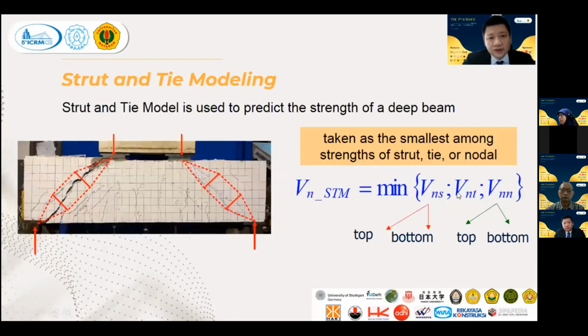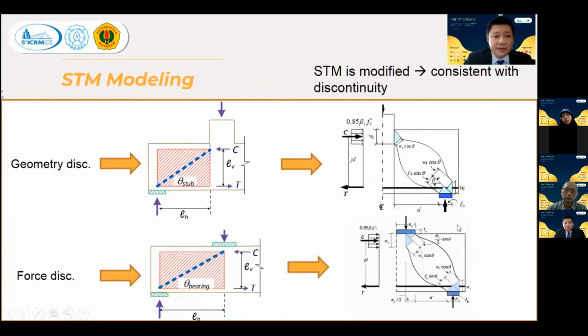Next, we try to use strut and tie modeling to estimate the strength. As we know, for the strut and tie modeling, we estimate strength at five locations: strength of the strut at top and bottom, strength of the nodal zone at top and bottom, and strength of the tie. Here, we try to modify a little bit the ACI strut and tie modeling. For specimen with column stub, the strut area is modified as shown in this figure. So we don't account for the column stub in here because it's bounded by the geometric discontinuity.